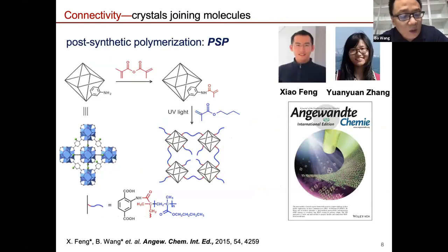So one example here, we use a very simple MOF, a zirconium MOF, UiO-66. We graft the surface and then treat such a nanoparticle as a monomer and react it with another monomer, in this case either methyl methacrylate or butyl methacrylate, as a reactant.